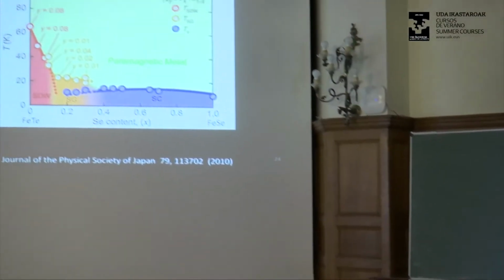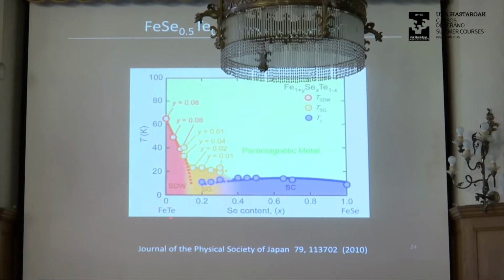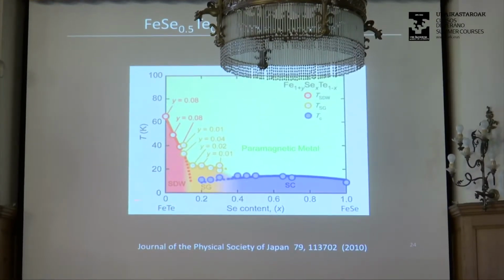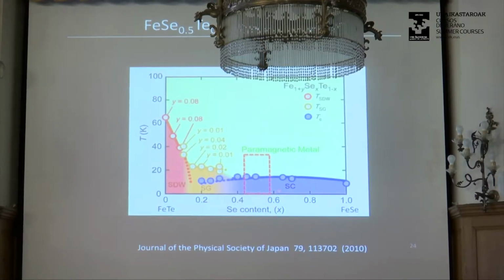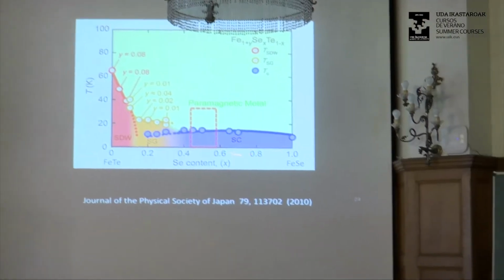So here's the phase diagram. The only reason I show you this is to show you that FeTe is actually not a superconductor. It's a spin density wave material. FeSe is a superconductor. So actually, superconductivity survives quite a bit when you put tellurium into iron selenium. And it's somewhere around this that band inversion is expected to happen, right? Right in the middle of this phase diagram. So it's not band inverted on this end, but as you put in more tellurium, the bands are expected to invert and give you this topological surface state.